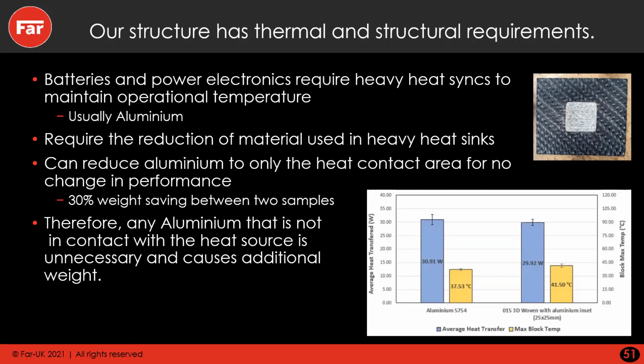The blue on the bar chart is the heat flow through the structure, and the yellow is the temperature of the heat source. And this heat source is analogous to the temperature generated from a battery cell or a power electronic circuit. So the way this experiment worked is we had a 40-watt heat source, which was applied over a 25 by 25 millimeter area on one side of the coupon, and a water cooling block is in contact on the other side of the surface. So our heat is flowing from our heat block through our structure and into our water cooling block. And by measuring the change in temperature in and out of that water block, we calculate the heat flow through the coupon.